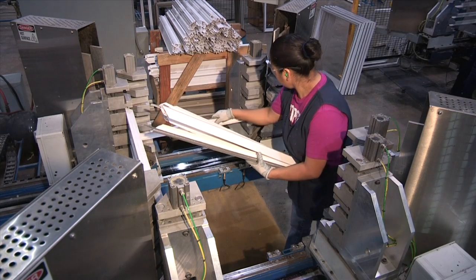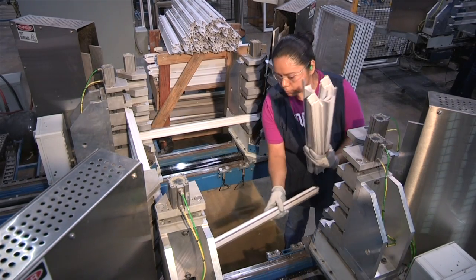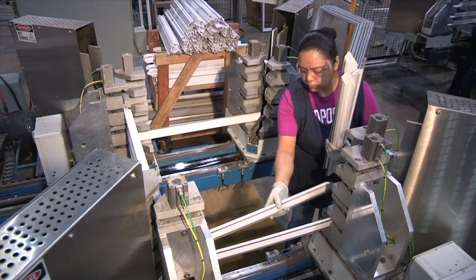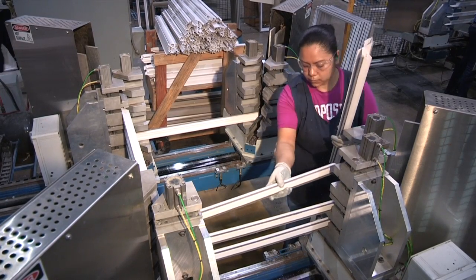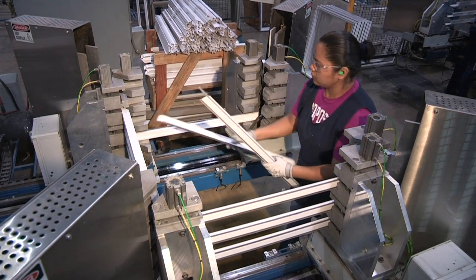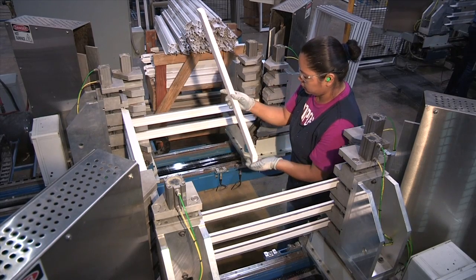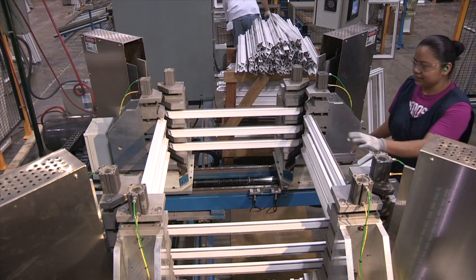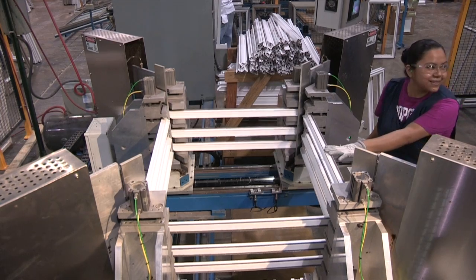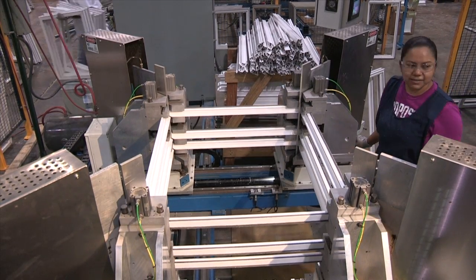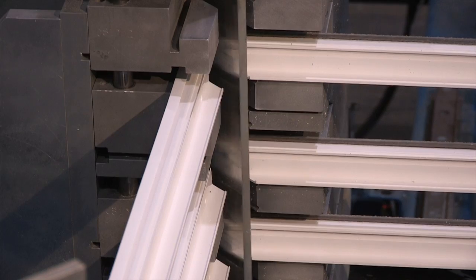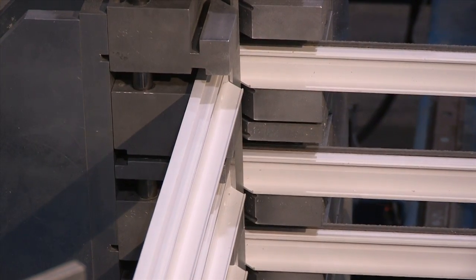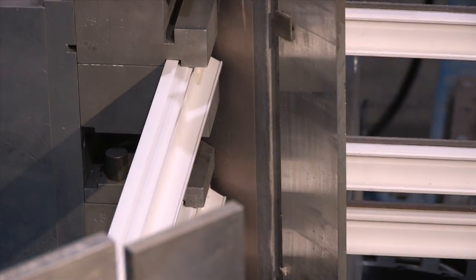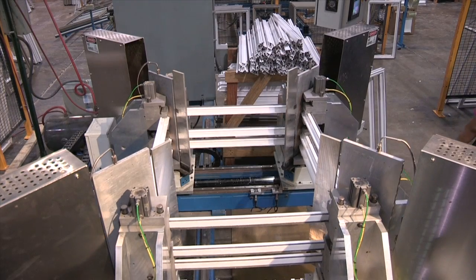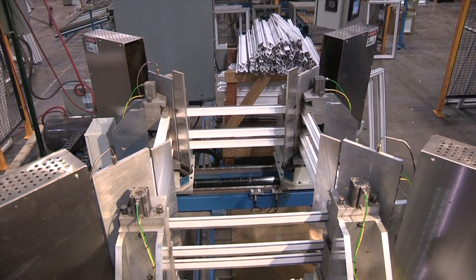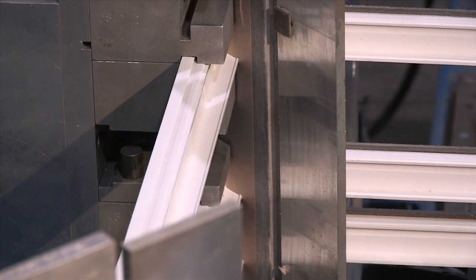We then load multiple pieces into a computer-guided welding machine. Our machines are capable of welding up to 4 individual frames simultaneously. First, and most importantly, squaring blocks are used to ensure the unit is welded square. Should the pieces be out of tolerance by more than 1/8 of an inch, the machine will not weld the unit. Then a heating block, whose temperature is 480 degrees Fahrenheit, melts the ends.